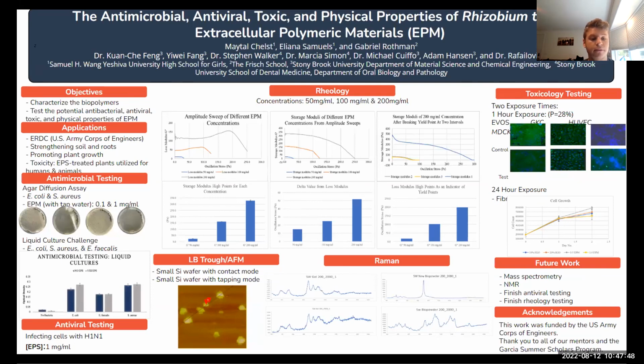In addition, the yield point where the EPM begins to break and the loss modulus is at its highest point, as well as the delta values, which is the amount of stress the EPM can withstand between its yield point and breaking point, were observed to increase tremendously with higher concentration samples. Finally, we wanted to see if the EPM could recover from being pushed past its yield point. Therefore, we broke the EPM down in the rheometer at its highest concentration and retested 30 minutes later. The results showed that the EPM had values for elastic modulus, which indicated that it was able to make a recovery.